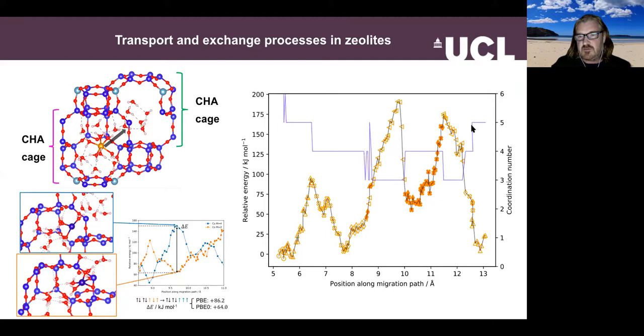Not only are there large changes in the coordination number, which is shown in blue, all these different points here with triangles, crosses, diamonds, and so on, they all represent distinct point group symmetries of the metal as it traverses through these cages. And then something that I hadn't really expected to rear its head, not only do we see large changes in coordination in the aqueous environment, but also you see changes in the preferred spin state. And the energies involved are really quite dramatic. So in this case, it's cobalt, and we're going from high spin to low spin, depending on how far along the transition pathway we might be.